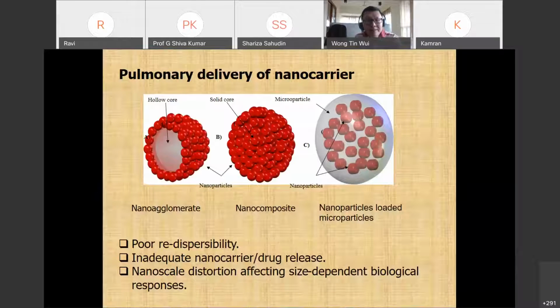Right. Now, over the past 10 years, due to the exhalation tendency of nanoparticles, various researchers have designed various microparticles for inhalation. Principally, we have nanoagglomerates, nanocomposites, and nanoparticles encapsulated in microparticles. Now, all these systems experience poor redispersibility. Hence, we may not get any nanoparticle in the deep and peripheral lung. A lot of times, due to the polymeric substances encapsulating the nanoparticles, the nanoparticle or even the drug cannot be released for the intended action. And worse still, in the process of making microparticles, your solvent and polymeric material may actually distort the size of the nanoparticles. This is highly unfavorable because uptake of nanoparticles by cancer or even normal cells depends on size features.